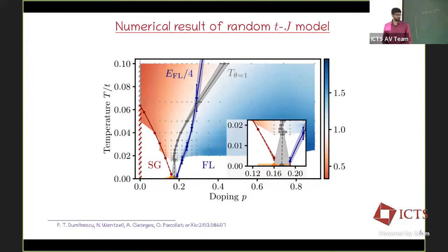But no one has tried spin polarized ARPES. I think that's a very difficult experiment. Yeah, that has not been done. Even measuring the dynamics of the spins has been a pretty challenging thing. If you recall, I showed you yesterday one of the measurements in this strange metal phase where they measured the density correlator. I think that's one of the very nice experiments, and one of the rare examples. Of course, there are a few other experiments that have been done in the strange metal and overdoped region, but I would say they are very few, especially in strange metal, because it's just very difficult to do experiments there.